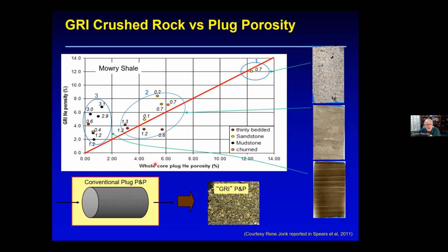And typically, at core labs, they have these all automated. It's about 20 minutes that they'll do a Boyle's law helium expansion, and then they'll measure it. So when we're in the sandstone, okay, we're at 12% porosity. And here I have the crushed rock porosity for contrast. But 12% porosity in the crushed rock shows it's 12% porosity. When we're in kind of the siltstone, lower permeability, smaller pore size, there's a bit of scatter, but it's in the kind of 5 to 7% porosity. And the numbers that are on here are the weight percent TOC in the sample.